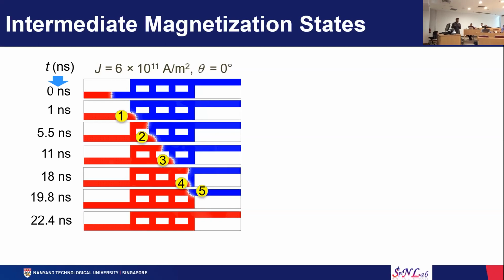Now, the previous simulation was for a single pinning site. Here we have taken all 4 segments. This is the initial state where the domain wall is inserted, and in the forward time scale it moves in the forward direction as current is applied to these devices, and the domain wall gets pinned at different pinning positions. These positions are numbered in yellow, and the blue color indicates magnetization in the up direction, and the red color is the down direction. At the end of 100 nanoseconds, at the final state, you can see that everything is red. So the domain wall completely sweeps the device.